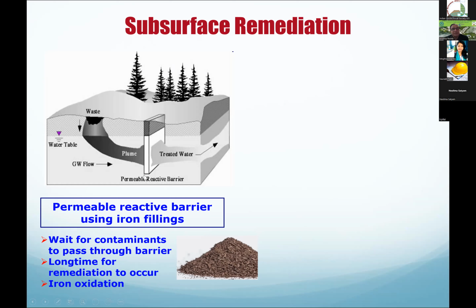But the biggest problem with this technology is that you dig a trench, and they put the material in, and you have to wait for the contaminants to pass through the barrier. So the natural or site hydrogeology is going to control the treatment, because the water has to flow through that. Groundwater flow in general is very slow, so it will take a long time. And if this iron is exposed to the atmosphere, the iron gets oxidized, and its reactivity will be reduced significantly. So that's the problem.